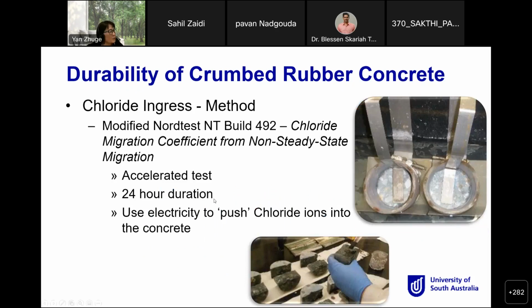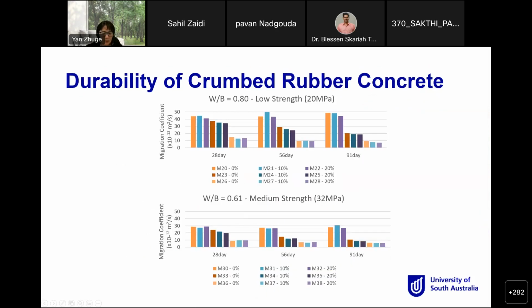Another test we did was the chloride test. We're using the modified NT BUILD 492 method, and we did an accelerated test for 24 hours duration, using electricity to push the chloride ions into the concrete. So that is the testing result for the lower strength, 20 megapascal, and that is for the medium strength of 32 megapascals, for all these three different groups of the testing.